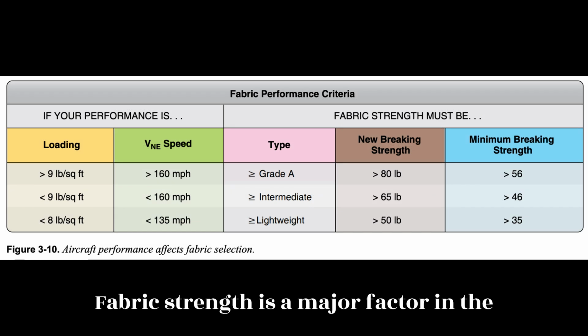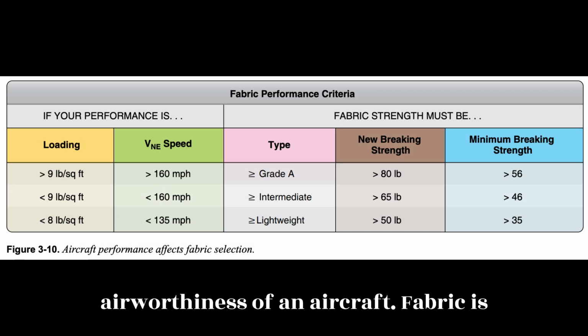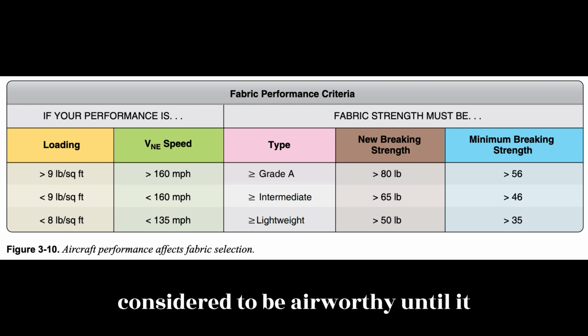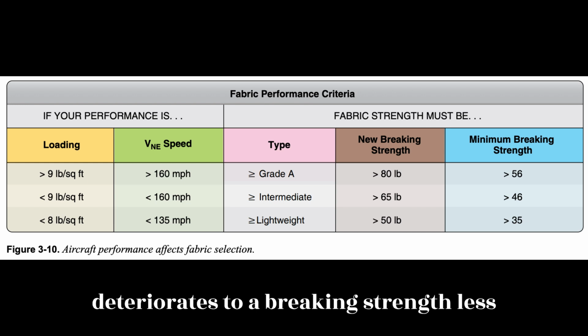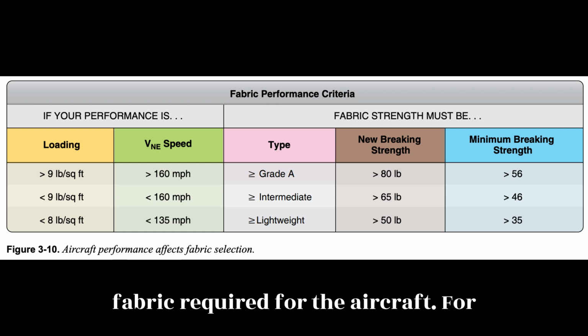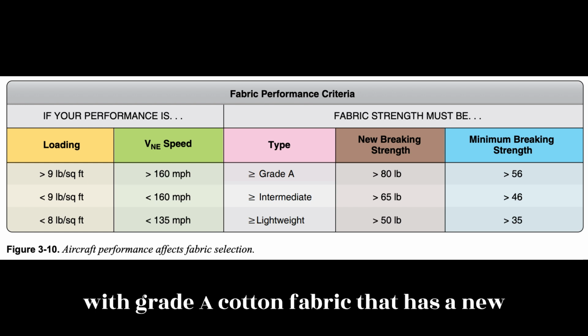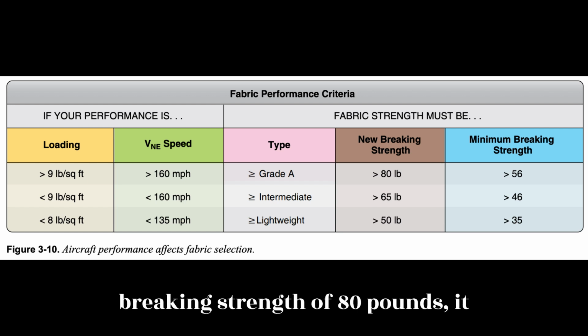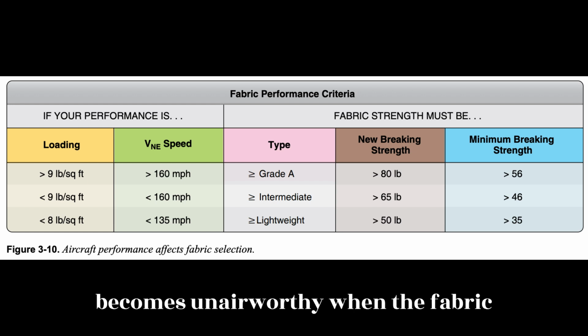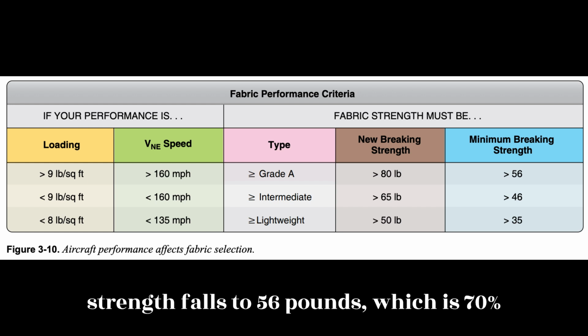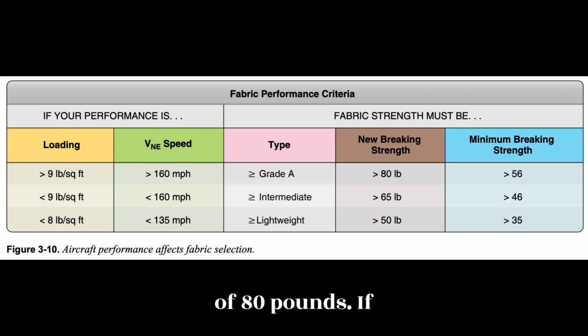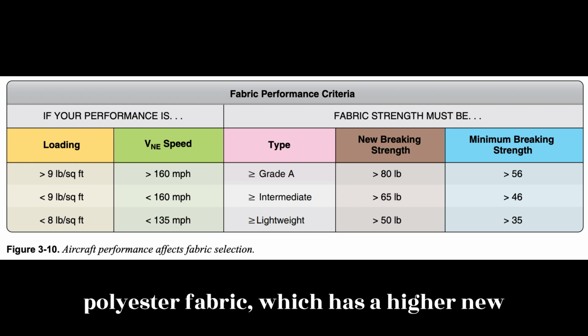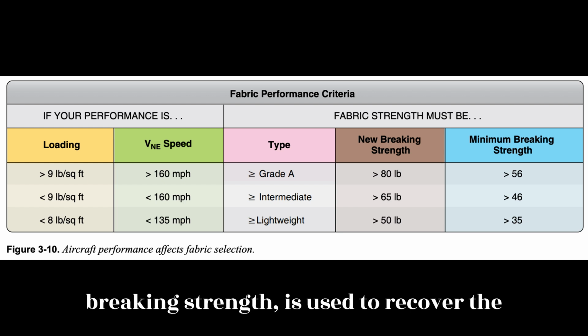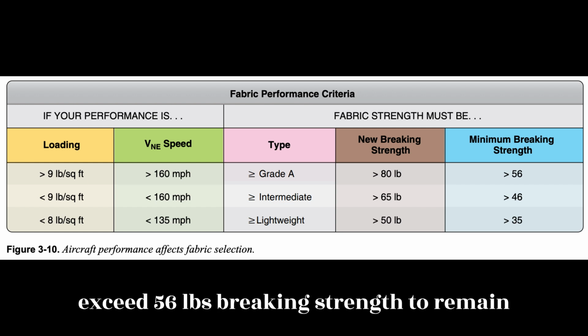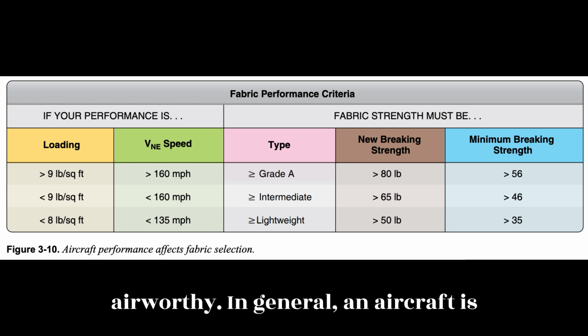Fabric strength is a major factor in the airworthiness of an aircraft. Fabric is considered to be airworthy until it deteriorates to a breaking strength less than 70% of the strength of the new fabric required for the aircraft. For example, if an aircraft was certificated with grade A cotton fabric that has a new breaking strength of 80 pounds, it becomes unairworthy when the fabric strength falls to 56 pounds, which is 70% of 80 pounds. If polyester fabric, which has a higher new breaking strength, is used to recover the same aircraft, it would also need to exceed 56 pounds breaking strength to remain airworthy.